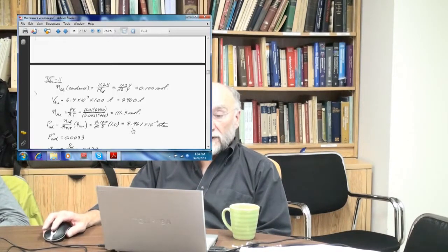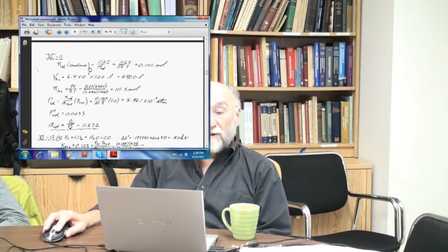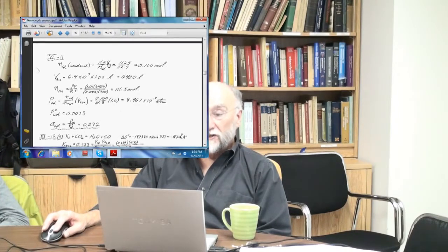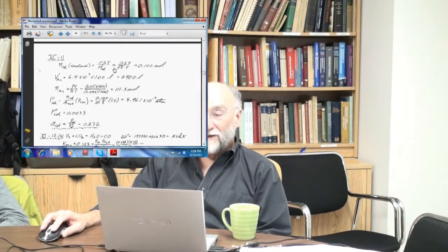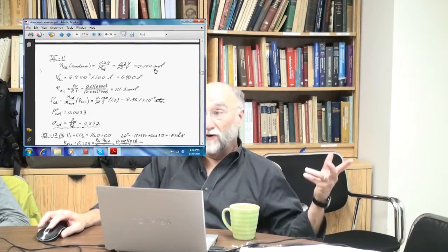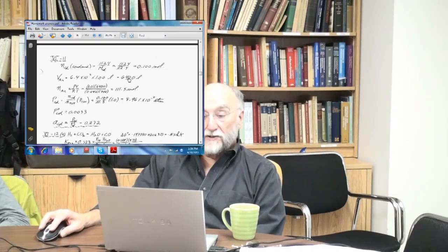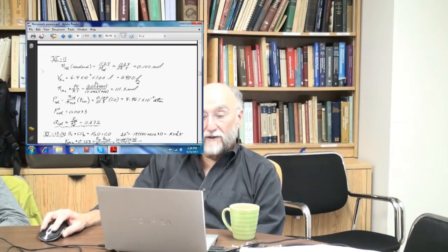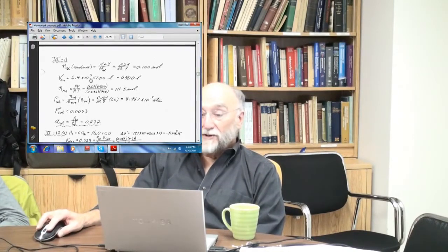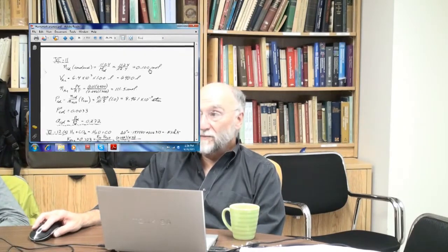So, the number of moles of cadmium that condensed: we said that during a certain amount of time you had 11.24 grams of cadmium condensed, which just happens to be one tenth of the molecular weight of cadmium. So 0.1 moles of cadmium were formed in the condensate. During that time, this is the volume of argon that passed: 6,400 liters passed during the 6.4 times 10 to the minus 3 hours. Okay, so 6,400 liters of argon contain 0.1 moles of cadmium.